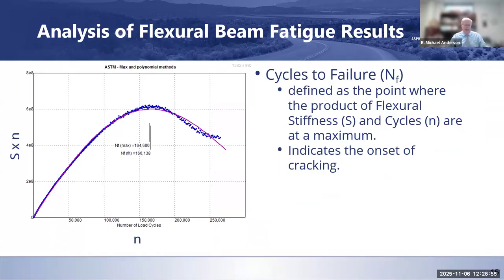So how do we analyze this data? In the original version of the procedure, failure was defined as the number of cycles at which the stiffness dropped to 50% of the original stiffness. That's how failure was defined. It was called N sub F. It was really based more on unmodified asphalts than on modified asphalt, but it was believed to represent the point where microcracking would develop into macro cracks, and then you would eventually cause the stiffness to drop more dramatically.